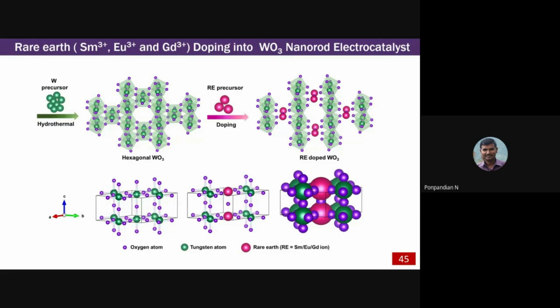Because this material, especially gadolinium, is magnetic, we wanted to improve the efficiency of catalytic activity through a magnetic field also. For that reason we added gadolinium in this kind of nanocomposite. And in the next set, the 3D transition metals, you all know that iron, cobalt and nickel are magnetic. In that way we have added all of them together with some co-doping, iron, nickel and so on.